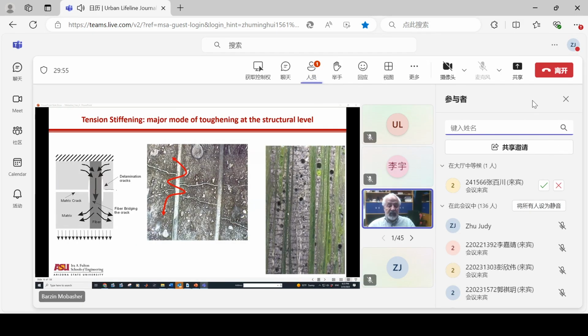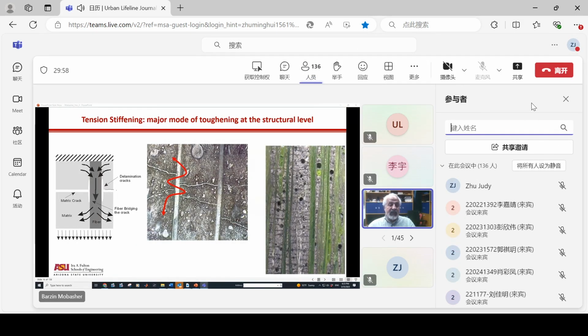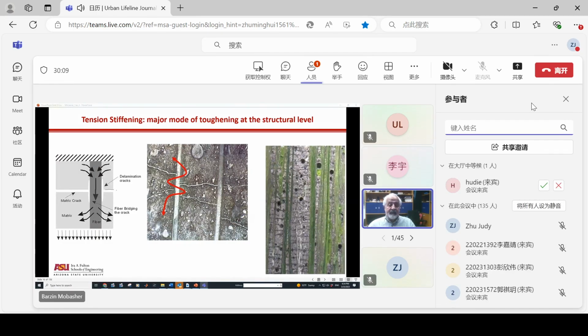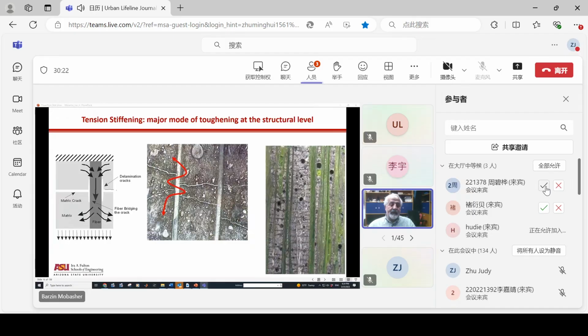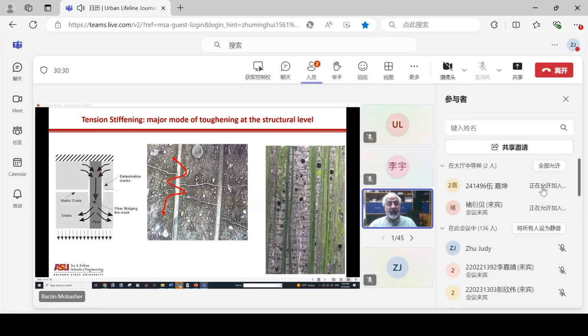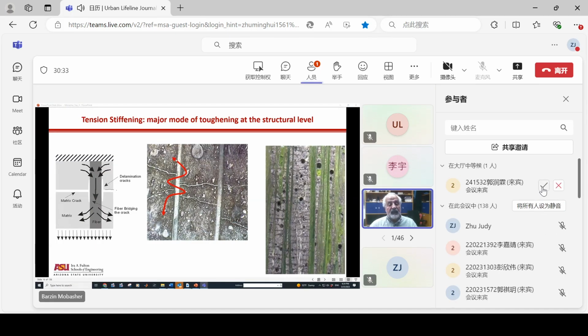So if you look at these pictures, these are microstructural pictures, and you see how the load from the matrix goes as a bridge onto a fiber, travels across the crack, causes the delamination, and then sheds away. So technically speaking, although I have two sets of parallel cracks, in any matrix here, the load jumps across here, jumps across here, jumps across here, and across here. Just like the game that kids play by jumping over a small stream and not getting wet. That's how the load is being transferred through this path. And we don't take that into account. We don't provide for this.